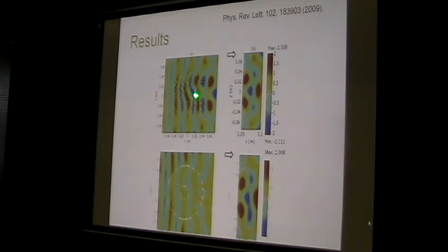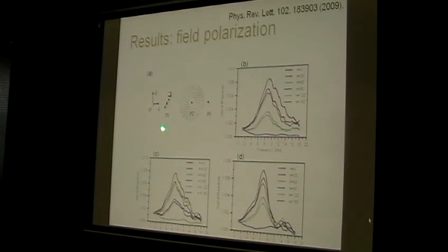And then you can see that indeed the fields are being rotated by the device there. We designed it with 30 degrees, and in fact it works very well. And this is another proof that you use a very small dipole, and you can measure the field outside. You can see that the field is maximum, aligned at 0 degrees, both inside and outside. But inside here, where we purposely designed a rotation of 30 degrees, you will see that the field becomes maximum when the field is at 30 degrees.